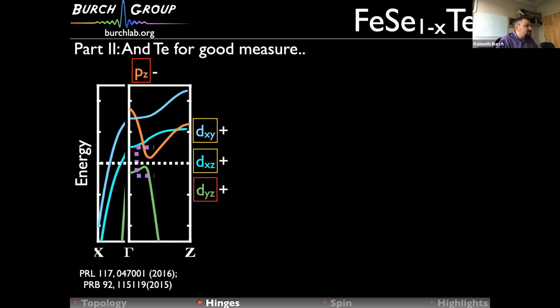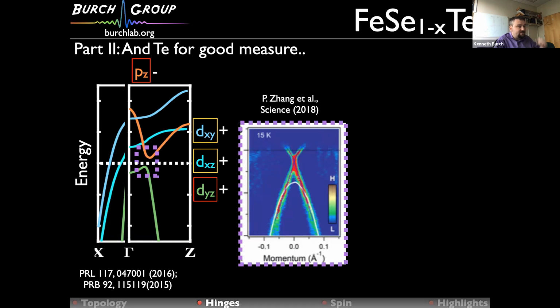Okay, so since then, in 2018, there was some nice work from Shik Shin's group. They claimed to observe these surface states using laser ARPES. They showed up roughly where they're supposed to be. There's evidence that there's spin momentum locking, et cetera, et cetera. I think in fairness, there's not consensus in the ARPES community, although maybe Ming can say more about whether this observation is correct. I think it's still quite controversial.